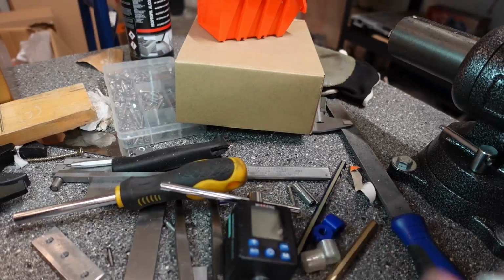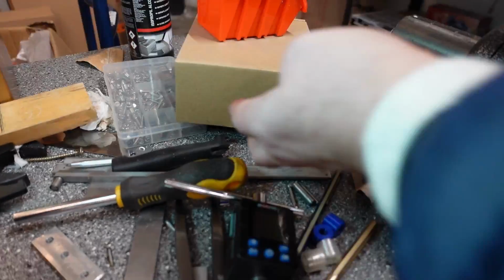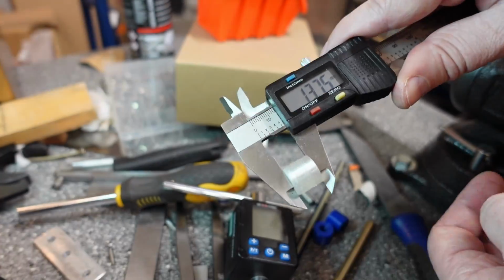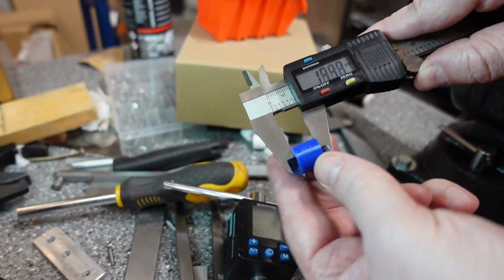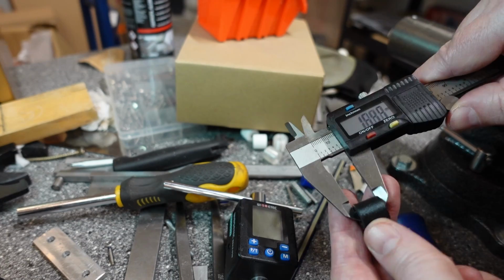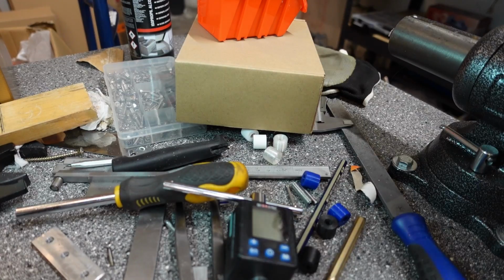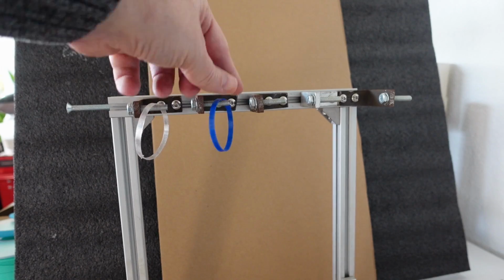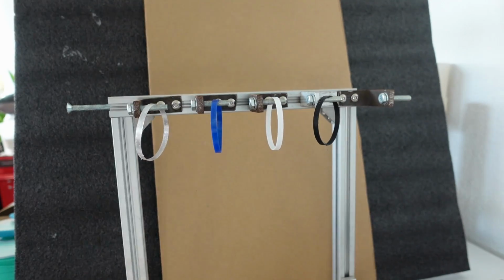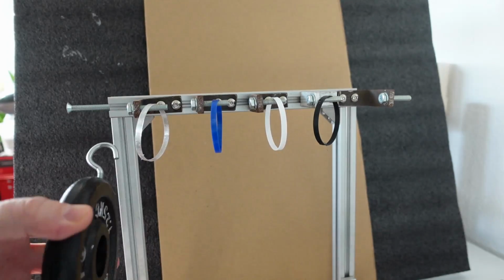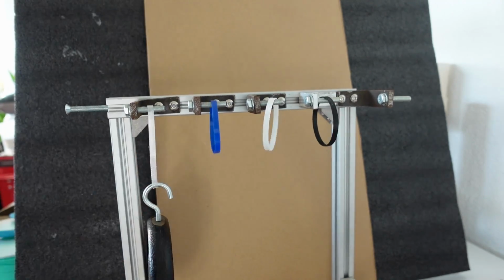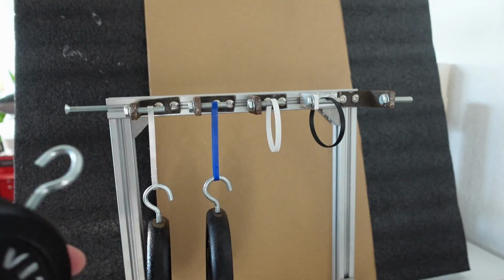Here I'm measuring their permanent deformation after half an hour. The original length is 15 millimeters and they were compressed 3 millimeters for 1 day. I will show you the numbers in the results part. This is my creep test for the TPU filaments. The thickness of this test object is 0.8 millimeters and the load is 1.25 kilograms.